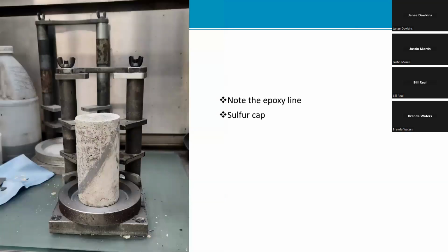And if you want to look at this, this is the epoxy line that you can see on the material. Now, usually when they're about to test this for strength, they would put sulfur caps on top. The purpose of the sulfur caps is, if you have the concrete, it may not be totally leveled. So the sulfur caps put it on a leveled or an even playing field.